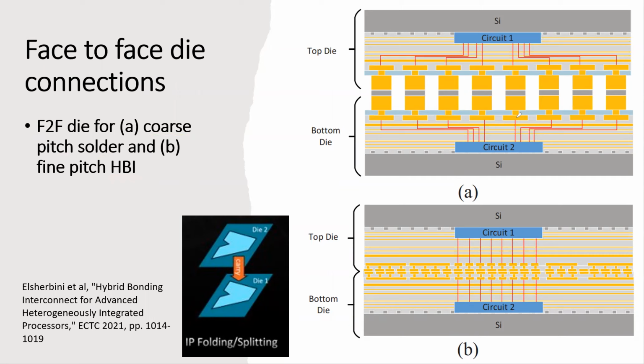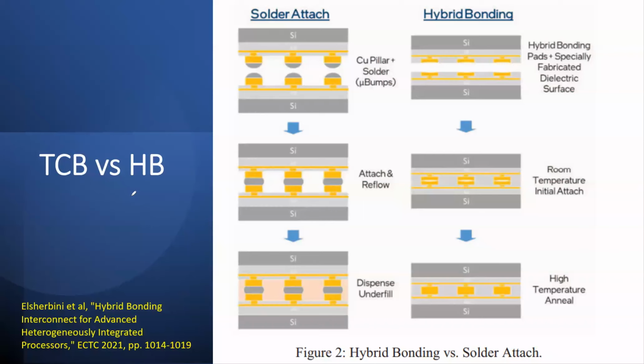You can see the difference between them. Here, this is copper and this is solder, right? You press them together and then you form a die. It's very easy to see the packing density versus the interconnect density. This is much, much smaller than this one, right? A factor of 10 to 100 or more. So this is the reason that people will have to move to hybrid bonding. And then you ask, why is that? That's thermal compression bonding versus hybrid bonding.